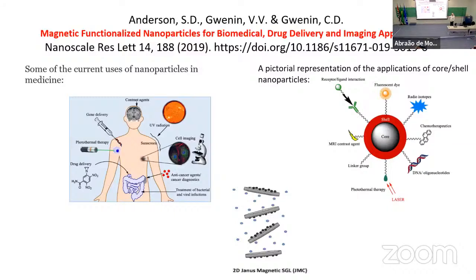The advantage of using the clays could be, this is something I have not proved, that we could increase the sensitivity of such a concept, because we have much larger surface area available than you have in a core shell particle. So we could capture more, and we can use a magnet to pull it out, just like here. That's the idea. We are working on that.